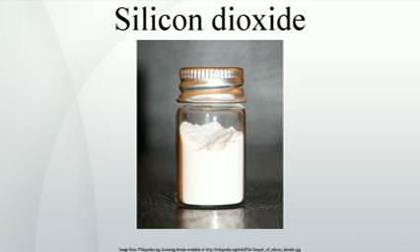Laboratory or specialty methods. From silicate esters. Many routes to silicon dioxide start with silicate esters, the best known being tetraethyl orthosilicate, TEOS. Simply heating TEOS at 680 to 730 °C gives the dioxide. Similarly, TEOS combusts around 400 °C. TEOS undergoes hydrolysis via the so-called sol-gel process.